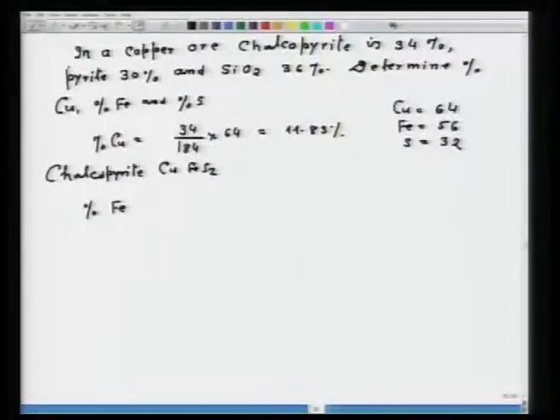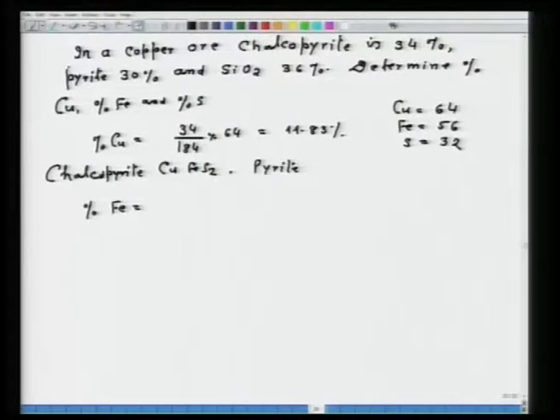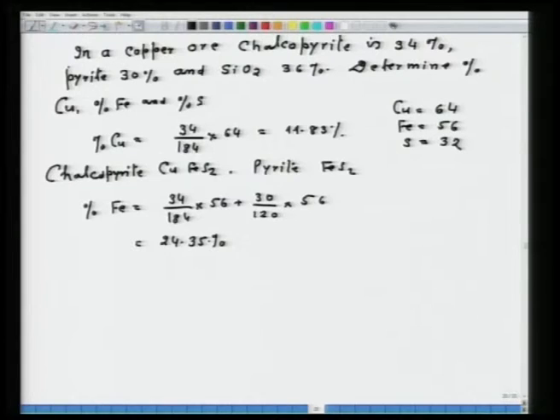Now, similarly, percent iron. Pyrite is FeS2. So, percent iron is coming from two sources: 34 upon 184 into 56 plus 30 upon 120 into 56. I hope you can add both of them, and that will be 24.35%. This is the percent iron.